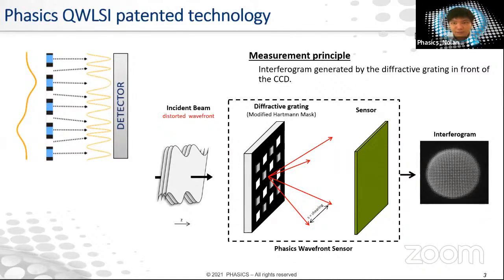So how it works is basically that when you send incident light, for example a flat wavefront or a distorted wavefront, it will be diffracted by the grating, and after that, most of the energy will be put in the first orders of diffraction, so plus and minus 1 along the x and y axes. Now, these four replicas of the beam will then propagate and interfere on the sensor. What we analyze is basically the modulation of frequency on the raw image of the camera, which we call the interferogram. If the wavefront is perfectly flat, you get a periodic interferogram. But if the wavefront is distorted, then you can see here that on the edges, the frequency is higher, or the oscillation of the same function.